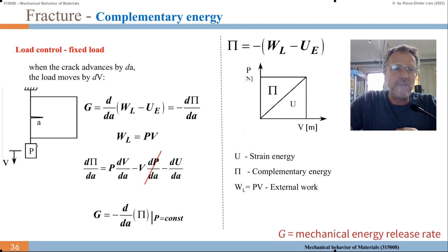So again, consider this situation where we have a constant load, just a weight hanging here across the crack. As the crack propagates and becomes longer, the lever arm becomes longer, so we increase the stress around the crack tip. And then G equals d over dA of WL minus UE, where WL is this square and UE is this triangle here. So we can say it's the opposite triangle, pi.